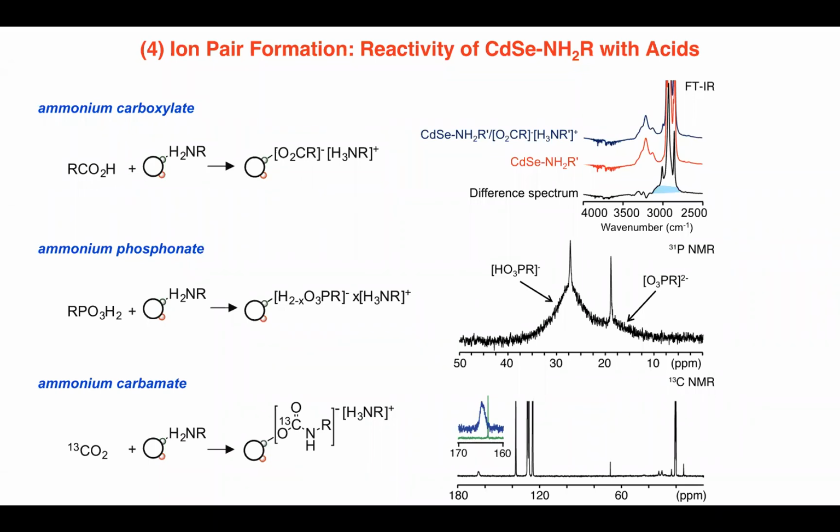Another very important reaction that you'll find is the reaction of CO2 with primary amines. If you take a bottle of liquid primary aliphatic amine off the shelf in your lab and you take the cap off, you'll find a bunch of white crust in the threads of that bottle. That is an ammonium carbamate salt that forms upon reaction with CO2. Liquid primary amines are used to scrub carbon dioxide out of gases in industry. So if you're trying to take CO2 out of the methane that you drilled out of the ground in the North Slope of Prudhoe Bay, you scrub it by bubbling it through a solution of ethanolamine.